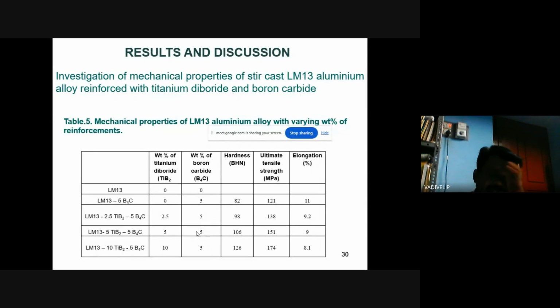See here, already we have discussed that the boron carbide is kept constant in all the levels, and we have varied the weight percentage of titanium diboride. Okay, and here is the hardness of the material: 82 BHN, 98 BHN, 106 BHN, and 126 BHN. And the next one is the ultimate tensile strength of the obtained material: 121 megapascal, 138 megapascal, 151 megapascal, and 174 megapascal. And finally, the percentage of elongation is 11, 9.2, 9, and 8.1. So these are all the mechanical properties we obtained by varying the weight percentage of the reinforcements.